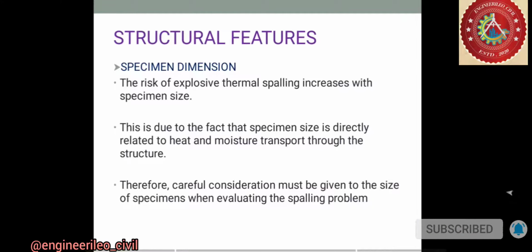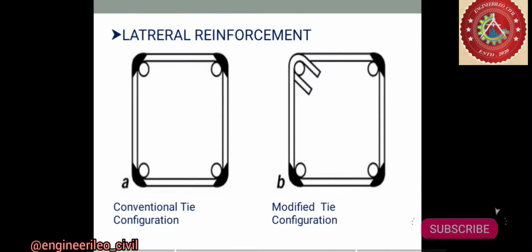Lateral reinforcement. Higher fire endurance in high strength concrete columns can be achieved by providing improved tie configuration, provision of ties bent at 135 degrees back into the core of the column, and increased lateral reinforcement with closer spacing. You might see in the diagram the lateral reinforcement, first in the conventional tie configuration and second in the modified tie configuration. These improved tie provisions also minimize the extent of spalling in high strength columns.